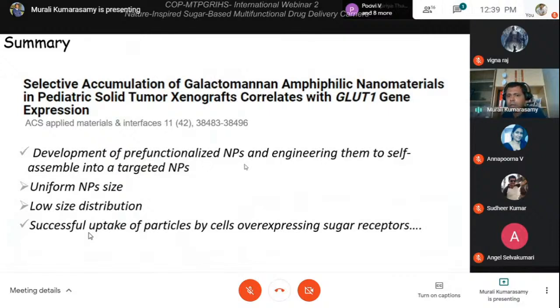So pre-functionalized nanoparticles, engineered to self-assemble into targeted nanoparticles. We got a uniform size of 150 nanometers and a low size distribution, because size distribution is a big problem. When you're producing nanoparticles, you get polydispersity. But in our case, we got exactly 150 to 160 nanometers. Another achievement was successful uptake of particles by cells overexpressing the sugar receptors, and we also got very good in vivo results, which I'm not going to present at the moment.